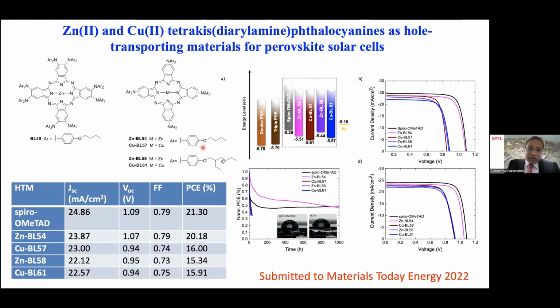And the butoxy substituents show better efficiency compared to the branched ones. The data is shown in this table. So this zinc phthalocyanine is giving over 20% efficiency with the butoxy, and compared to the alkoxy within the zinc family, it is coming down from 22 to 15%. Sorry, zinc to zinc, with butoxy to alkoxy, it is coming down from 20 to 15% efficiency.